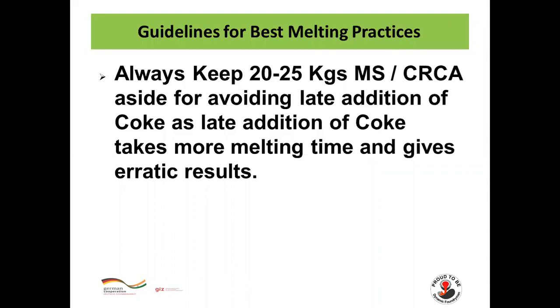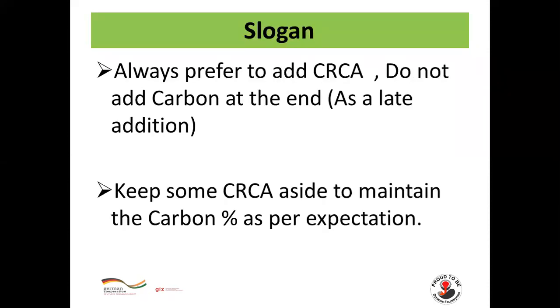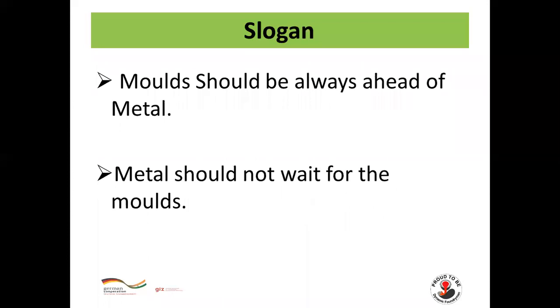Always keep 20 to 25 kgs of MS or CRCA aside for avoiding late addition of coke, as late addition of coke takes more melting time and gives erratic results, and most importantly it will hold your furnace and your power consumption will go up. Slogan: always prefer to add CRCA, do not add carbon at the end as a late addition. Keep some CRCA aside to maintain carbon percentage as per expectation.